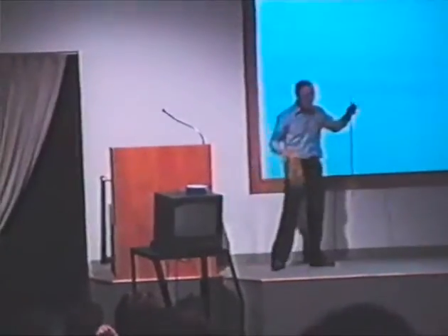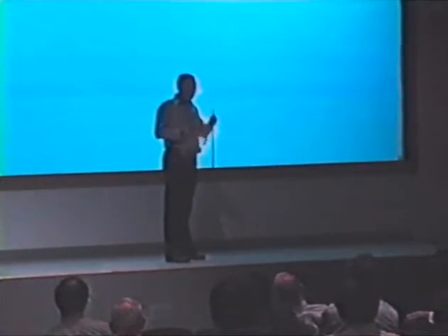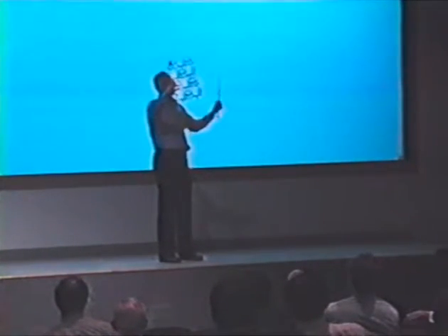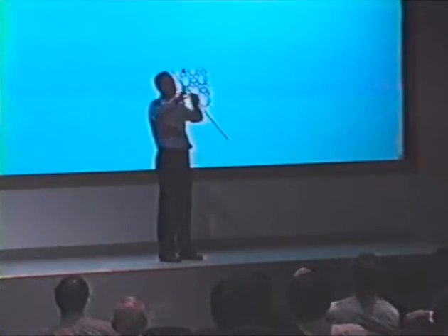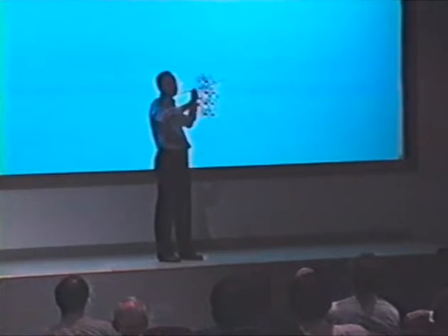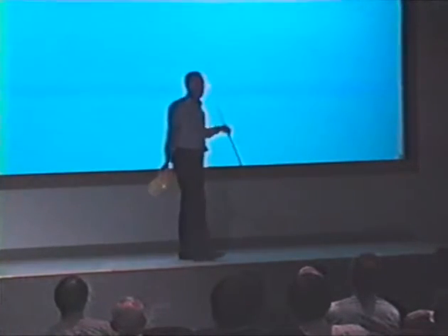Are you going to show us your model? I brought that. I thought it'll be available if anyone wants to take a look at it. Some people have more difficulty than others seeing what a structure is from a planar drawing. I hope you can see this. These are the chains of 5 rings which are running along this direction. They essentially hook together 6 rings and 10 rings. This is the 10 ring channel. You turn this perpendicular, you'll see the 8 ring channel. The two intersect. It's a 2-dimensional zeolite, as is barrerite.